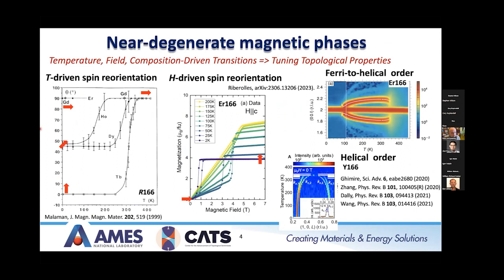So if you look at the left side here, this is an old graph from Malaman back in 1999. You can actually see, for the ferrimagnetic ground state, the angle away from the C-axis with decreasing temperature. If we look at the terbium, for example, all these materials seem to order above 400 Kelvin. The rare earth and the manganese seem to order at the same time. As you cool down, here it's easy plane, driven by the manganese easy plane anisotropy, but then as you cool down, the uniaxial rare earth anisotropy takes over for the terbium, and you get the overall ferrimagnetic structure now aligned along C.